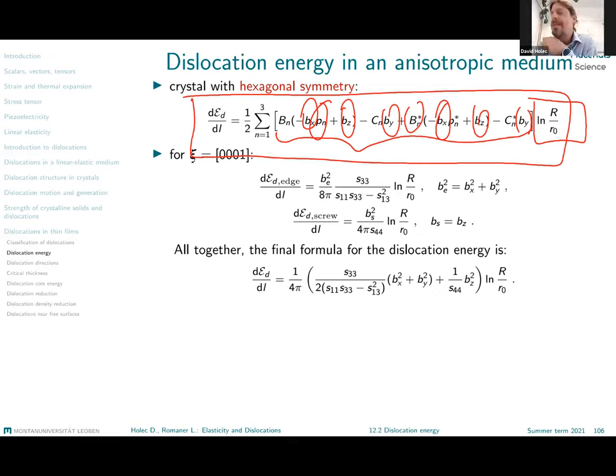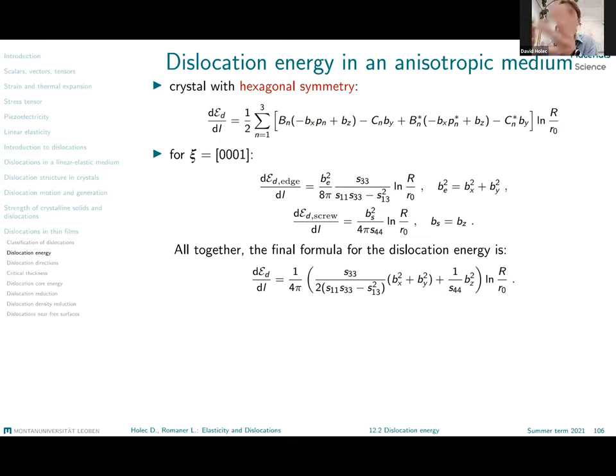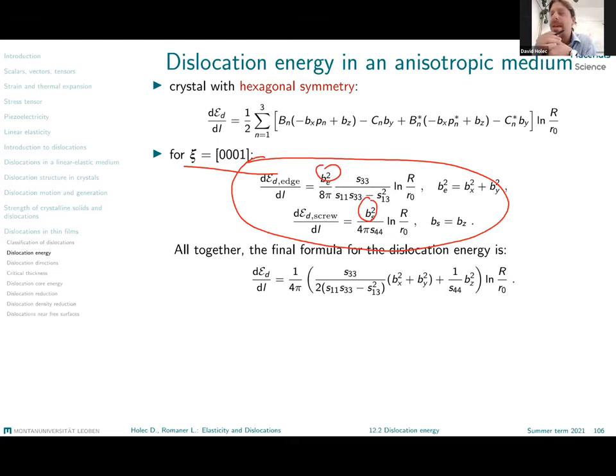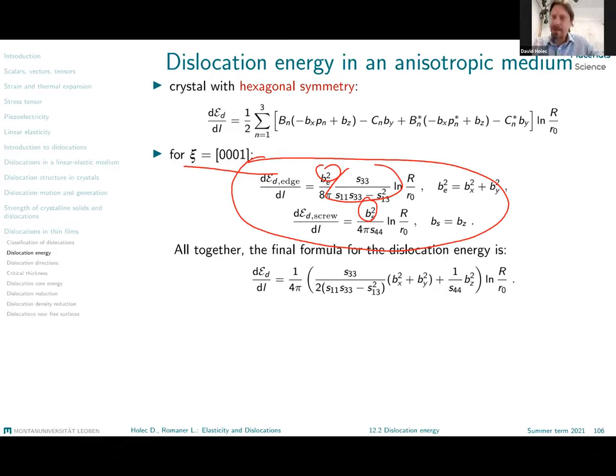This formula can be explicitly evaluated only for certain orientations and geometry. Here we have the example of the dislocation aligned along the 0001 direction, so along the hexagonal axis. We end up with formulae very similar to what we had in the isotropic case — again, there is the edge component or screw component, and we have the elastic compliances. Maybe a question here: why do you think the evaluation of the dislocation energy is way easier when the dislocation is oriented along the 0001 axis?